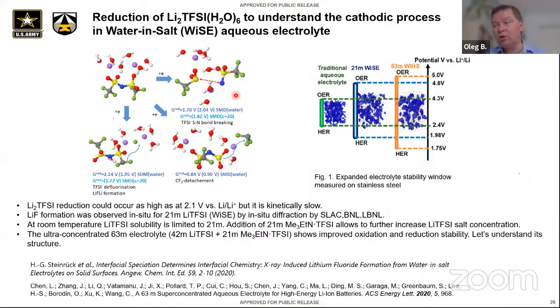And the Borodin group was proposing another idea with the anion being attacked by OH. Travis has looked at the other anion, triflate, and found that indeed that could be the case, but with a pretty high barrier of 1 eV at best, and most other barriers are close to 2 eV.